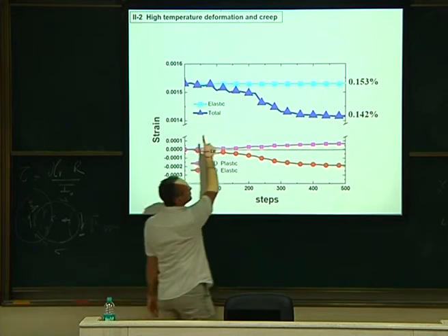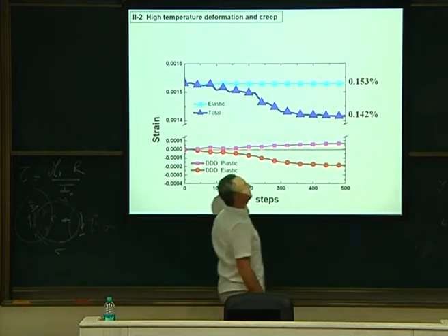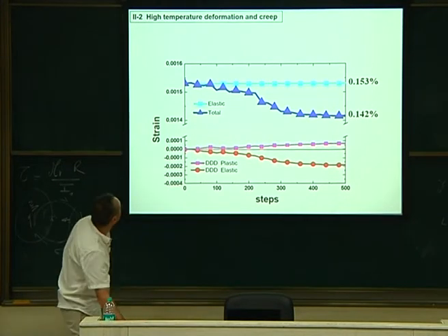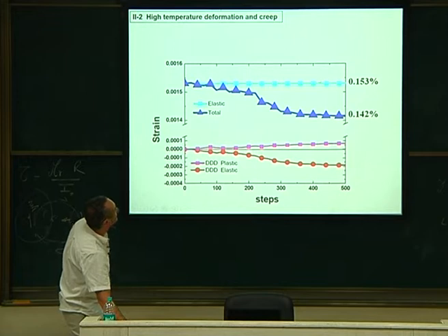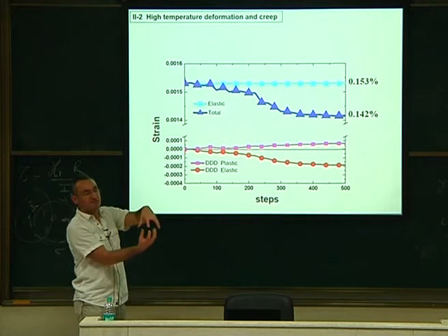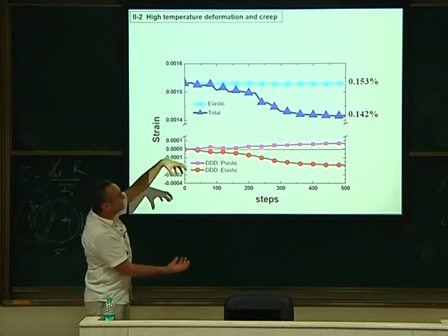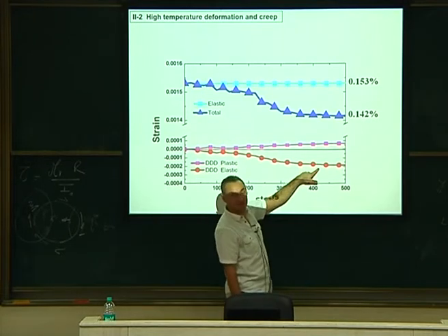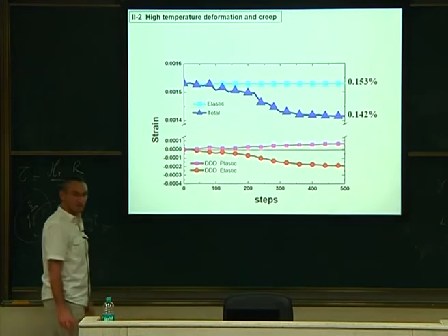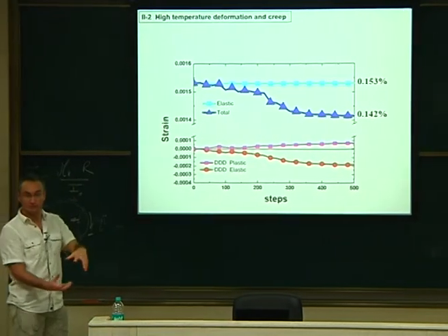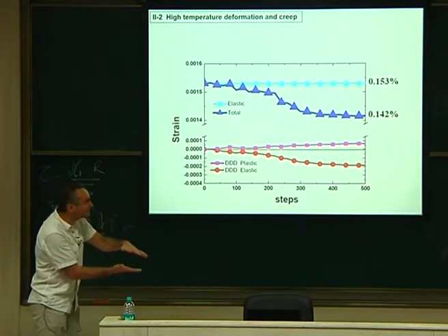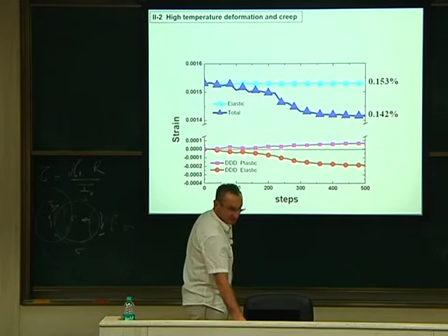So finally, you have the total deformation, which is negative, 0.1% compression, although you pull on it, okay? So first you have this 0.153 here, which was what you applied initially in your box, because you push on it, so elastically your specimen deformed like this, and then it contracts like that because of the elastic fields due to dislocations. You get those four curves? Any question on that? So it's strange, right? You pull on it, you have plastic deformation, that's correct, but you have elastic deformation that shrinks the specimen. So this is how it works.